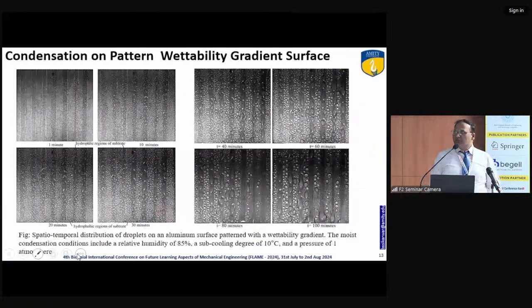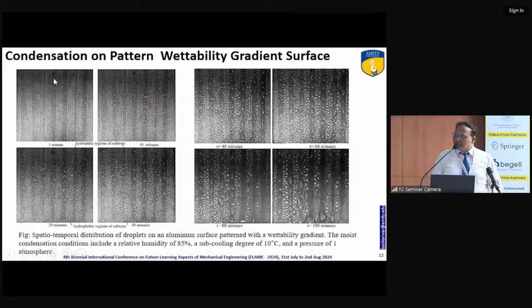So you can see we do the condensation experiment. I am not going to explain the experiment here, but what you can find out is what happens where the surface is hydrophobic. There is drop formation, and on the hydrophilic there is film formation. Because the drop at the interface is sucked by the wettability gradient to the hydrophilic region, it automatically cleans the surface for new condensation.